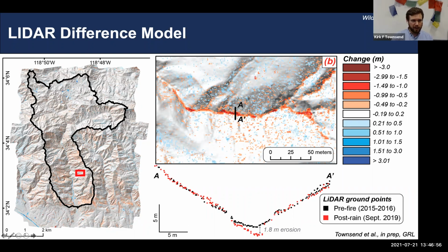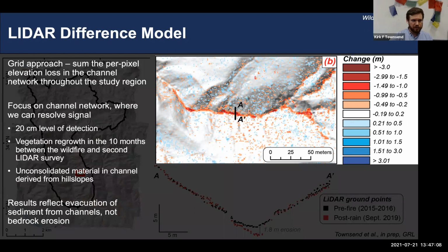Now we know from the overall difference map that erosion like this occurred in the channel network throughout the entire 60 square kilometer study region. So to understand what variables actually influenced the erosion, where it occurred, and how much of it occurred, I'm going to use a grid-based approach where I convert this difference map into a grid and then sum the per pixel change in that grid and convert that to a volume.